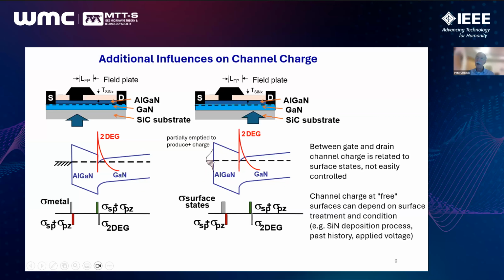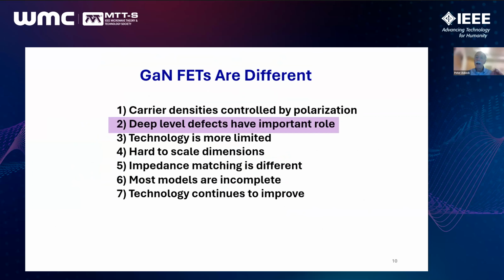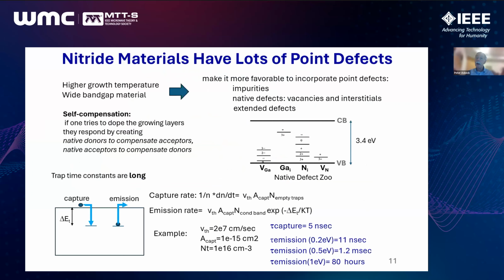The surface states themselves are things that, in most nitrides, are controlled by the past history of the material, the preparation technique, and in fact can be dependent on applied voltage. And the fact that the surface states are deep levels, and deep levels exist elsewhere in the material, is very important for gallium nitride behavior. The deep levels have an important role. They exist in part because gallium nitride has a high density of dislocations from lattice mismatch, typically on the order of 10^8 per square centimeter. But in addition to defects introduced via the dislocations, there are numerous point defects,